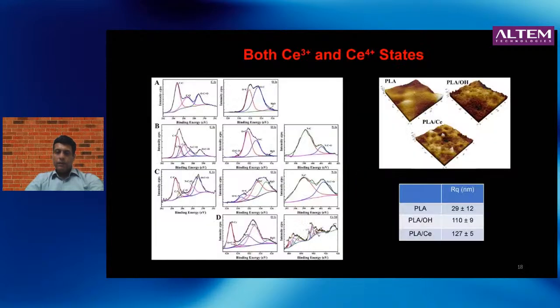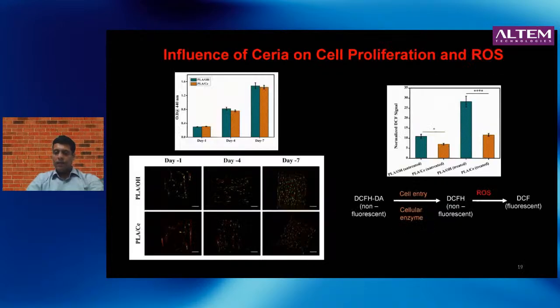And then we checked it with XPS, or X-ray photoelectron spectroscopy, and what we found here is that there are both Ce3+ and Ce4+ states. There's a mix of the two, which is great because that means the cerium can switch between the two states and help in modulating reactive oxygen species. When we looked at the surface roughness, it wasn't very different for the Ceria coated versus the one that had been OH treated. So the surface roughness wasn't different, but what was different was there were cerium oxide particles on these. So next we seeded cells on them, again the stem cells, and saw what happens.